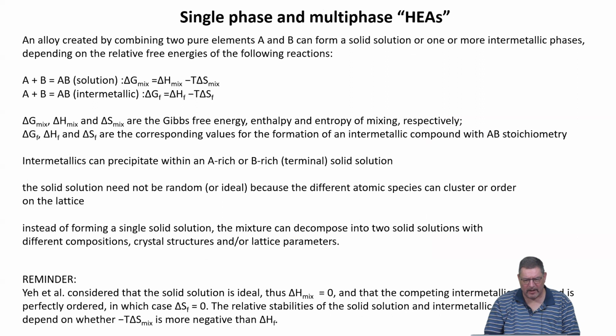Now, we also thought about single-phase and multi-phase high entropy alloys, while multi-phase is not really a high entropy alloy, this is why it's in parentheses. So single-phase and multi-phase compositionally complex alloys are important to look at, especially because for properties and property optimization, more and more it's recognized that a single solid solution phase will not fulfill all the needs. And we can use all the tricks we have learned from conventional alloys to make properties better also in high entropy systems by having second phases forming. Important is what I already indicated, that we then have to worry about the formation enthalpy of the intermetallics.